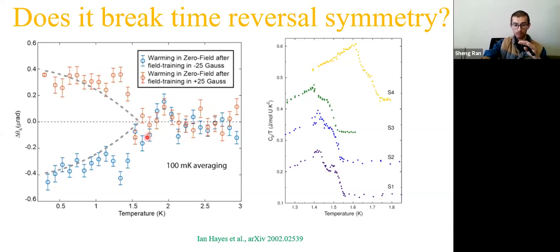Here, 1.5 is Tc. Below Tc, indeed, you have a non-zero Kerr shift. But it turns out the sample has time reversal symmetry domains. If you just shoot light on the sample, likely the domain size is smaller than the beam size, so you will get an average. And therefore, at the beginning, when they shot the light directly, they actually did not see time reversal symmetry breaking.